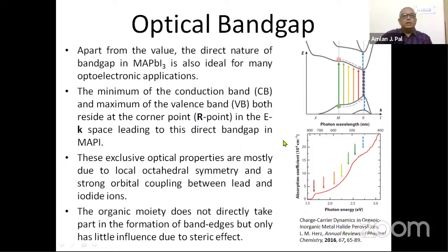And another thing is the band gap, this is the advantage over silicon, because silicon has an indirect band gap, is an indirect band gap semiconductor. And that is the reason you need a thick silicon wafer to absorb enough solar light to produce electricity from the solar cell. You need about 300 to 500 micron of silicon to absorb solar light, because its band gap is indirect in nature. Fortunately, the band gap of methyl ammonium lead iodide is direct.